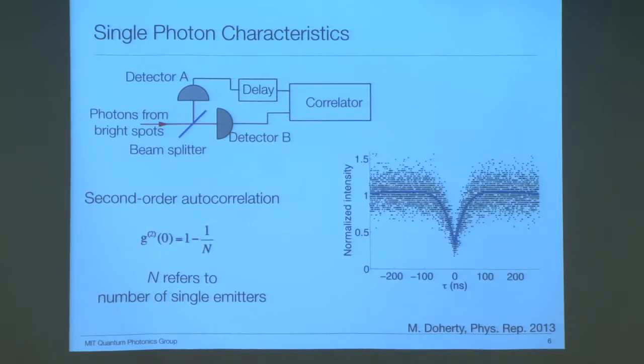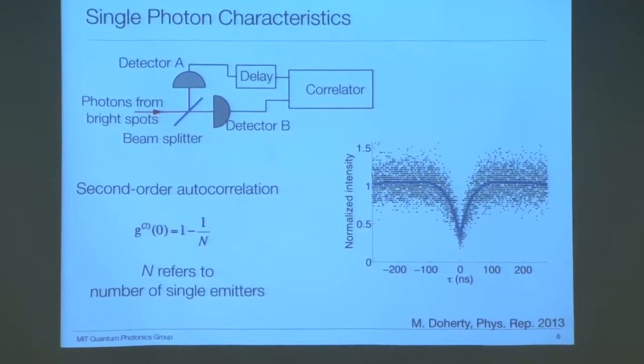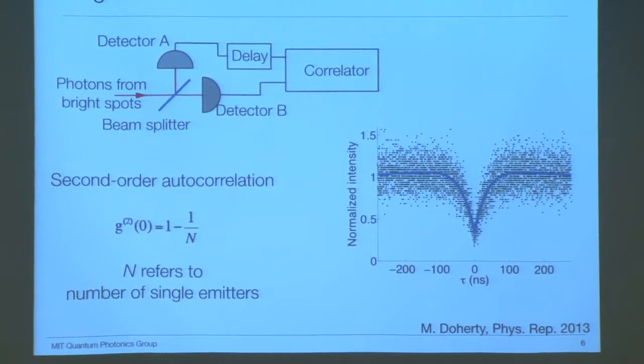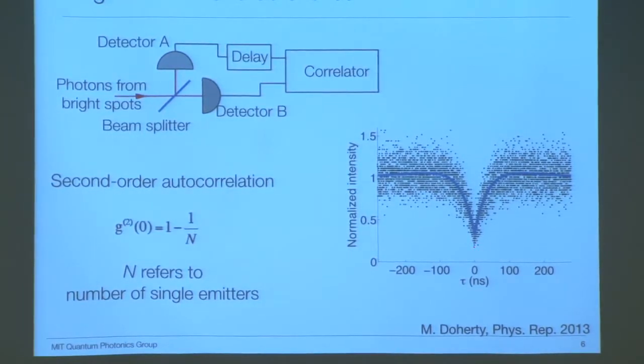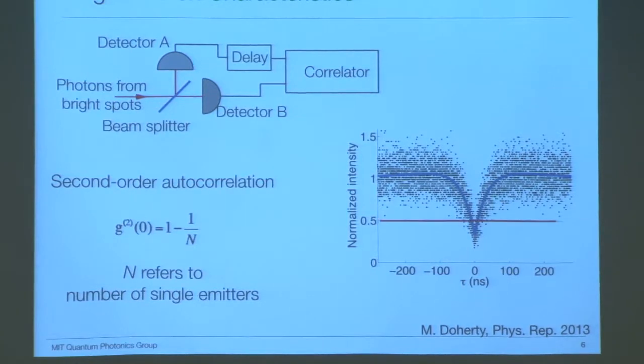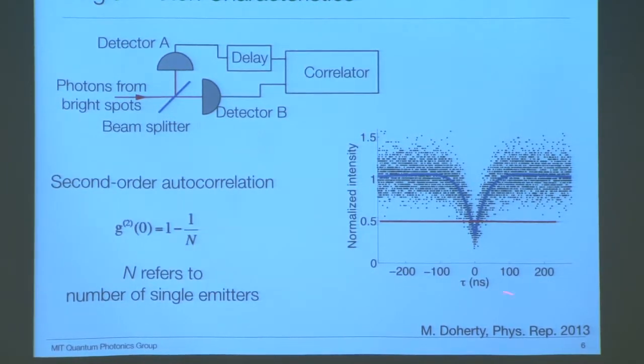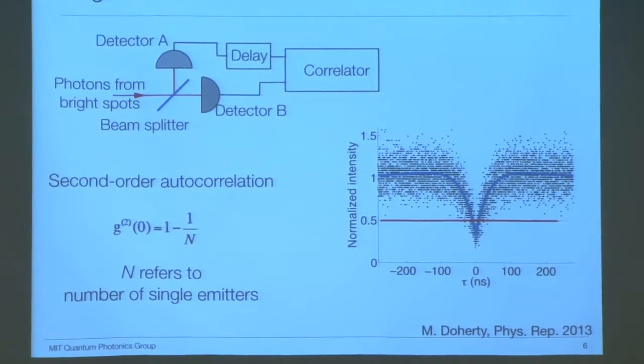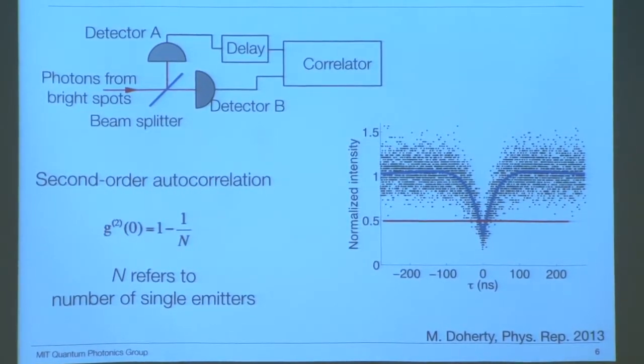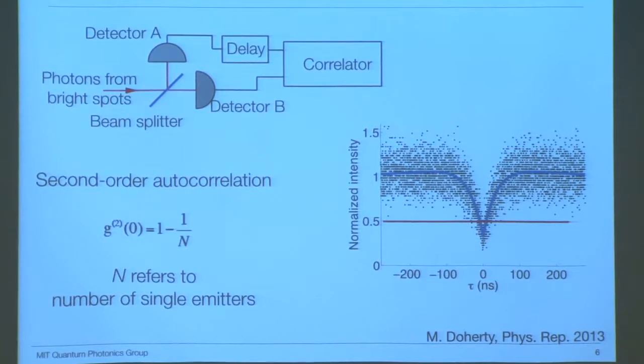In real experiments, the NV emission is often accompanied with some background fluorescence from diamond. That's why the g2 dip is normally slightly above 0, but still below 0.5, even for a single photon emitter. And we readily use this measurement to determine a single NV spin qubit. And this single spin qubit can be used in quantum information processing.